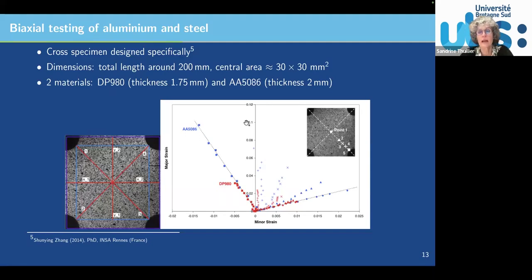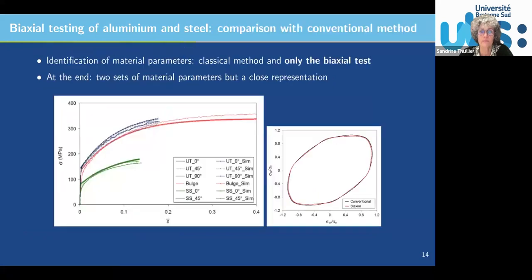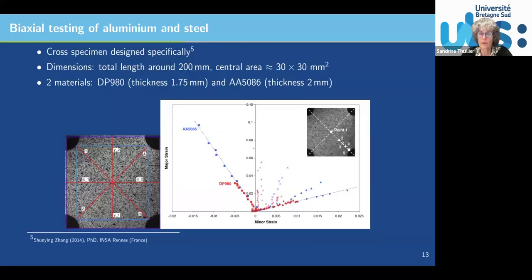So for aluminum, we reach higher strain. For dual phase, in red, strains were lower, but more or less these are the same strain paths. So meaning that with only one test, you can cover more or less 1, 2, 3, 4, and 5 strain states, and you would have needed 5 different mechanical tests in order to reach the same thing. So this is really the illustration of the interest of heterogeneous testing. And so what was done was to calibrate a mechanical model by inverse methodology. So it was in this case isotropic hardening with an anisotropic yield criterion, so Bron and Besson.